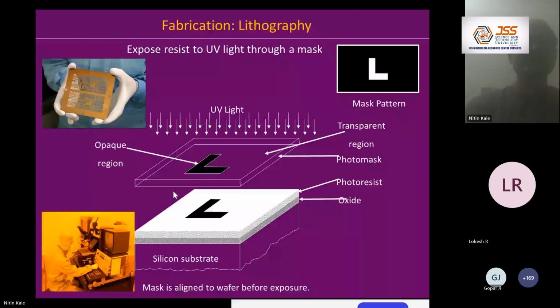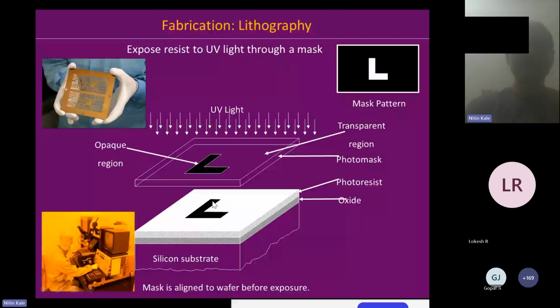This is the mask. This is the UV light, which is used for photo activation. This is a UV aligner machine inside a yellow room. The silicon substrate, the material of interest which you want to pattern, the photoresist on which you have designed, let's say, your pattern. So after you send your light through this, you have a structure which is like this, which has been, let's say, weakened. And after you do the development, the photoresist is removed from this place. Now, if you use an appropriate etchant, you will be able to remove the oxide.